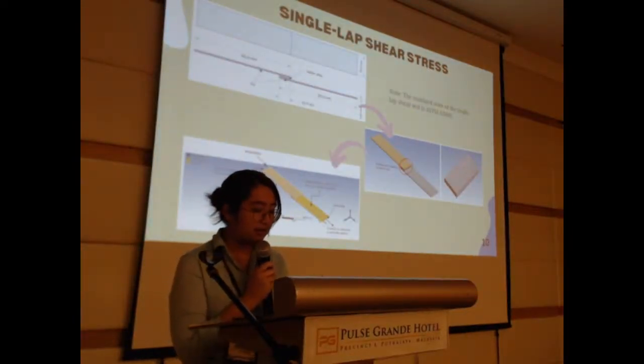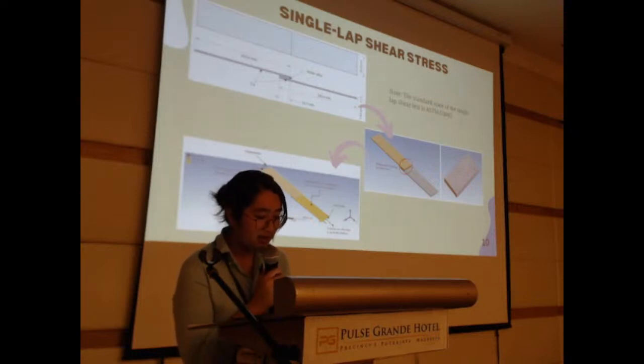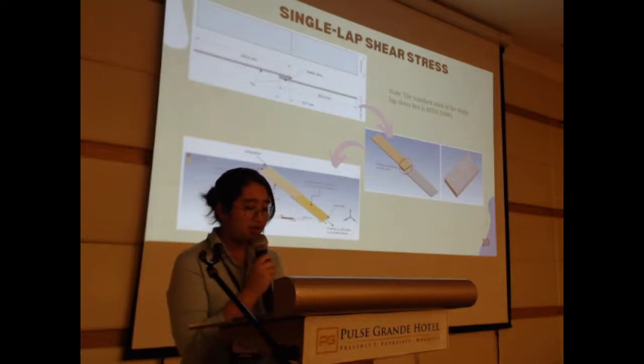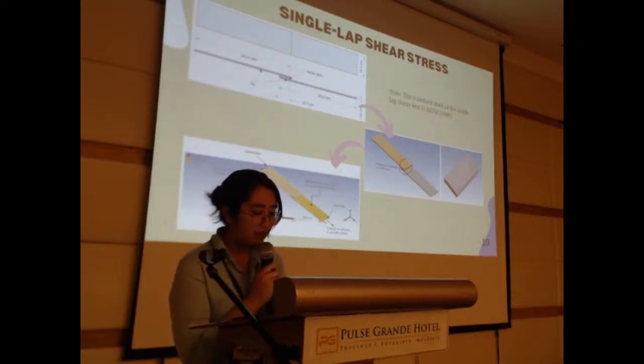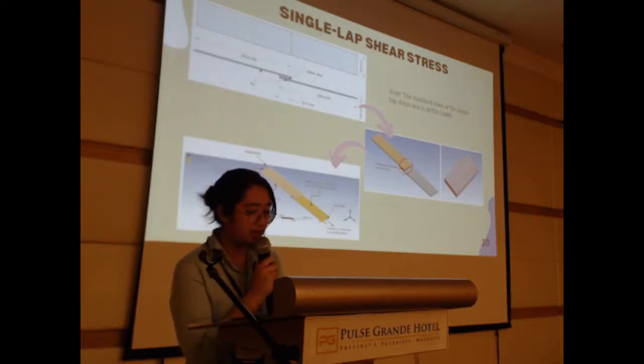And the single lap shear test is being conducted in a simulation form. So a 3D geometry of a single lap shear joint was constructed using SolidWorks software according to the ASTM D1002 standard. The geometry consists of 2 metal plates according to the dimensions shown here. And the copper was assigned as the substrate of the metal plates.